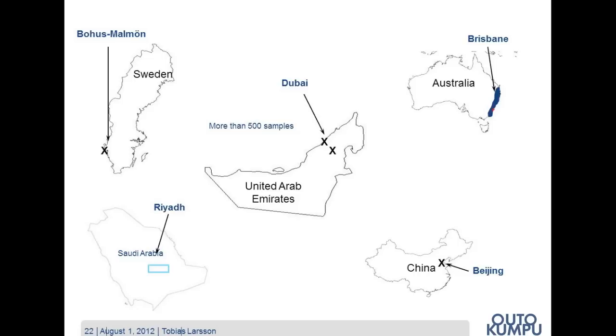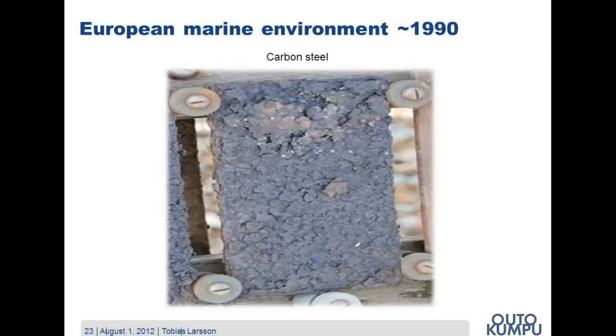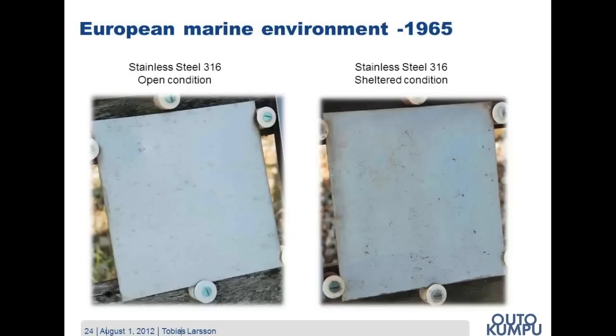So currently in Dubai, we have more than 500 samples. And today I will show you the results from the marine location, which has been exposed for a bit more than 2 years now. But here we can see a carbon steel sample that has been exposed in a European marine environment since 1990, so around 20 years. And as you can see, it has more or less totally corroded away.